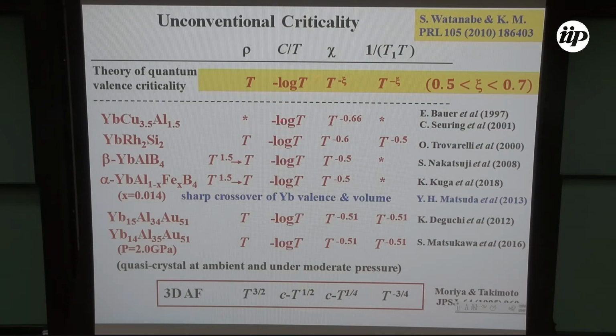Actually, on the basis of this Hamiltonian, Watanabe and myself developed the mode coupling theory, which explains the resistivity, C over T, and uniform susceptibility and 1 over T1T of NMR. It shows this kind of anomalous exponent. Xi is weakly temperature dependent, between 0.5 and 0.7. So there is a series of anomalous compounds which show unconventional criticality. These criticalities almost coincide with the theoretical prediction. This is completely different from the three-dimensional antiferromagnetic scenario published by Moriya and Takimoto, which gives this kind of temperature dependence for these compounds.